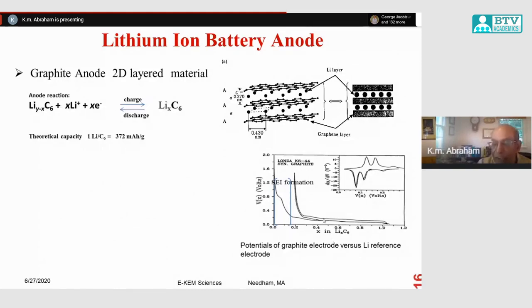It should come down to the graphite potential, very close to 0 volt. So you have this part of the capacity which is the reduction of the electrolyte to form a film on the surface of the graphite. That film formation is extremely important because that film protects the graphite from reacting further with the electrolyte when you continue to cycle your battery. This is what we call a solid electrolyte interface on the graphite anode.